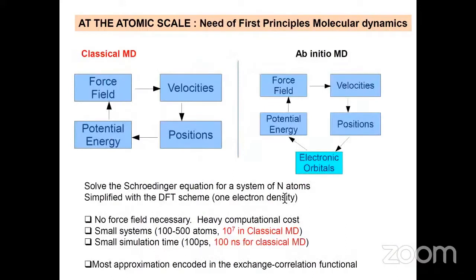So the very difference between classical MD and ab initio MD is that you use a density functional theory. That is, you reduce the whole problem, the electronic problem, to one electron density. That's typically the central work of Kohn and Sham. Of course, you have a price to pay, which is the introduction of a correlation energy and an exchange energy. But in principle, you basically solve the same kind of equations. That is, once you have got the electronic orbitals by solving the Schrödinger equations from the positions of the atoms and have computed the electronic density and then extracted the forces, you are able, using the same Verlet algorithm, to integrate the equations of motion for the ions to get velocities and ultimately positions.